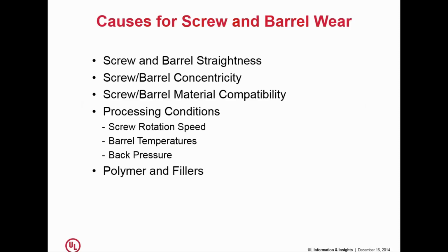And your process has to be set up properly. You have to have the right screw rotation speed. You have to have the right barrel temperatures, the right back pressure. These are all things that have to be developed during your process development cycle. And of course, your polymer and your fillers. But understand that it doesn't require a high degree of glass fiber in order to wear out a screw.